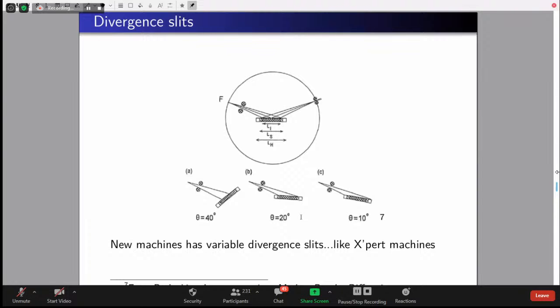In theta theta, you do not have any trouble. Easily it will be going up and down. But when we go for theta to two theta, your sample also moves, so the footprint is going to vary. So what people have done is they have an automatic divergence slit. For higher angles or lower angles, accordingly the divergence slit width will change. So a large amount of intensity will be coming in. That's why at higher angles we could get some intensity. The effect of the divergence slit is a little less, but the receiving slit width should be more. That should be automatically increasing such that at higher angles you have good intensity. That is my opinion.